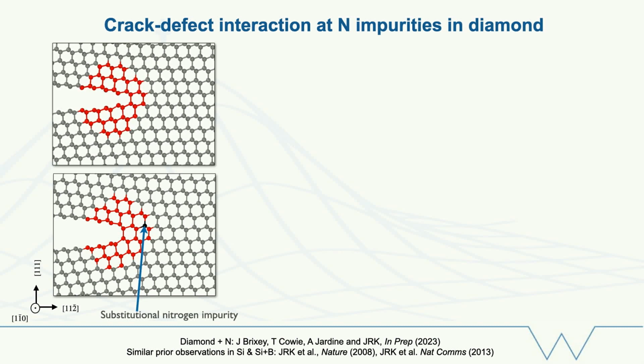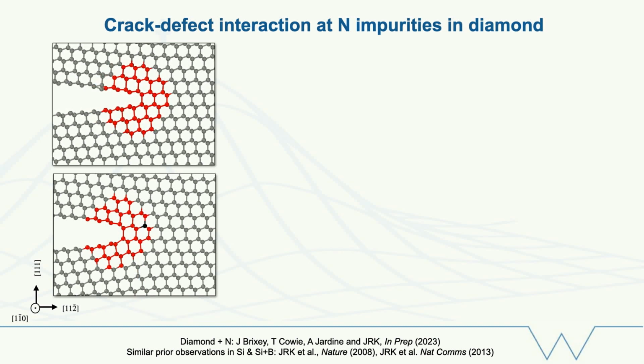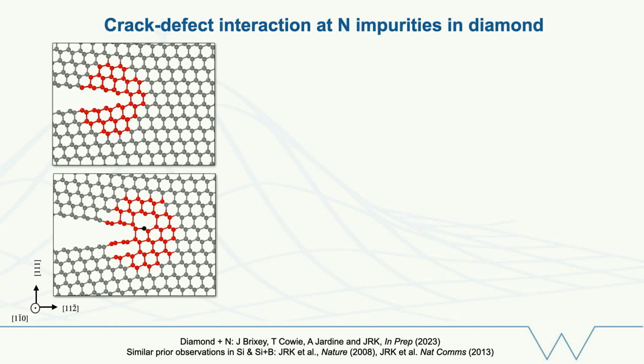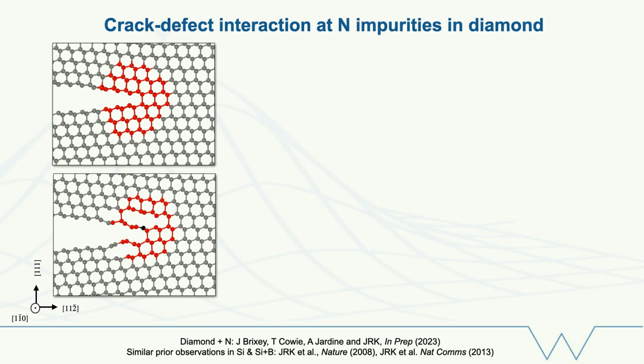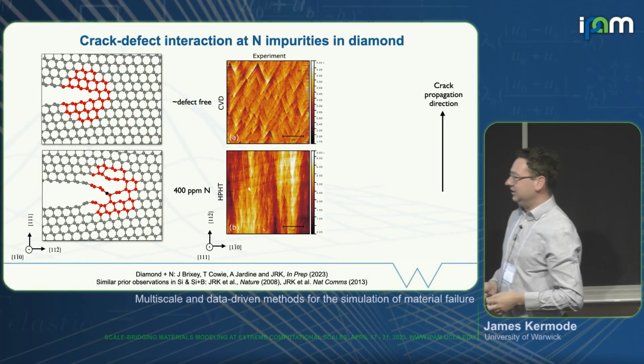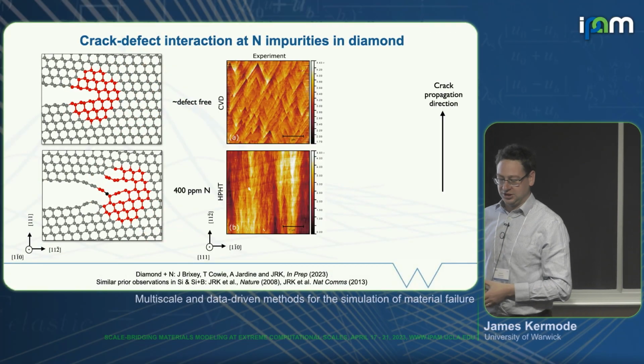And now we can look at what happens if we place just one substitutional nitrogen impurity ahead of a crack tip. And we can see what happens within the quantum region without any reparameterization. We get interaction between the propagating crack and that impurity, and it causes the crack to systematically take a step up by one cleavage plane. If this happens many, many times, it leads to experimentally observable surface features.